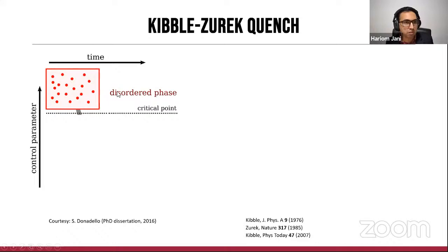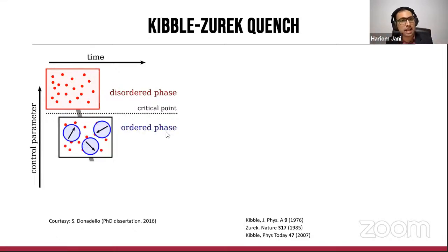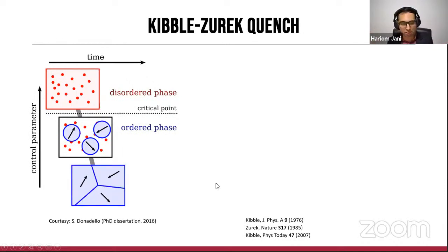So the idea involves the use of a system which starts from a disordered state, and as it undergoes a phase transition into the ordering regime, pockets of order emerge. Evidently, these would not be coupled to each other because they would be space-like separated for the order parameter communicating between them, and therefore they would not be aligned with respect to each other. When sufficiently below the transition, these domains would expand, and we would end up getting textures such that they have some kind of domain walls in the middle.